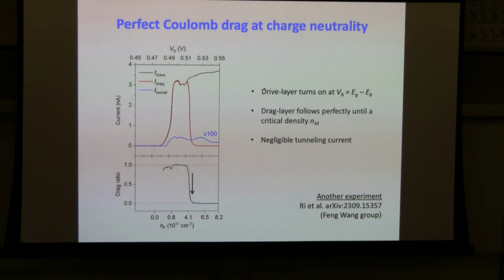So if you take the ratio, you can see that the ratio is equal to 1 in this excitonic insulator region, over this window here. You get a perfect Coulomb drag, where the whole current in the hole layer is exactly the same as the electron current, except that they are flowing in opposite directions.